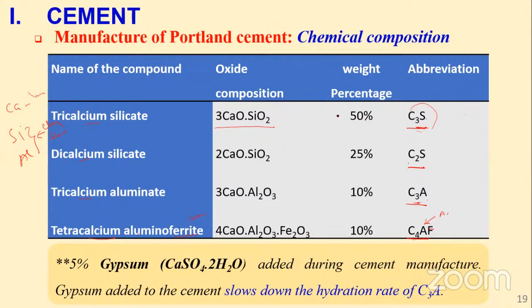Now, the composition is as follows. You see tricalcium silicate has the highest composition, followed by dicalcium silicate, tricalcium aluminate, and tetracalcium aluminoferrite being the least. So if you add the total of these, you are going to get 95%. So the 5% is gypsum, hydrated calcium sulfate, to make it 100%.